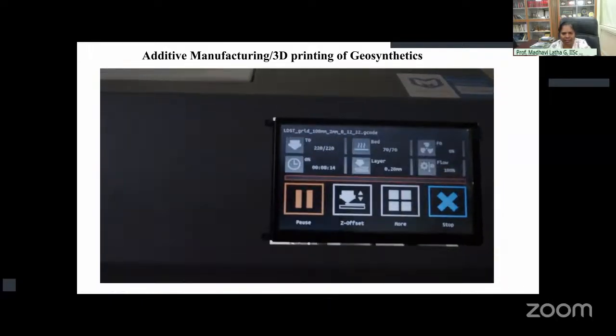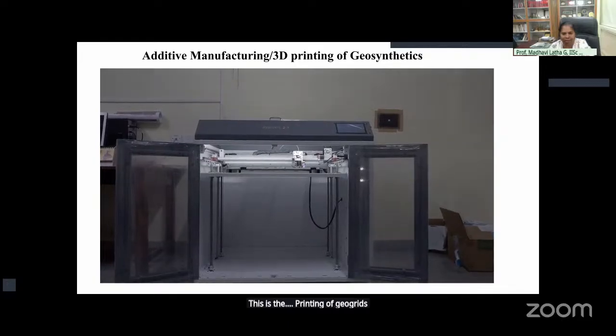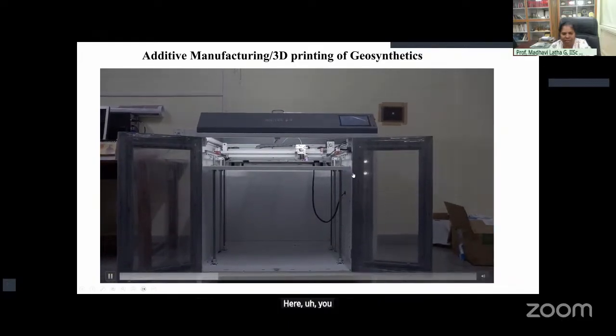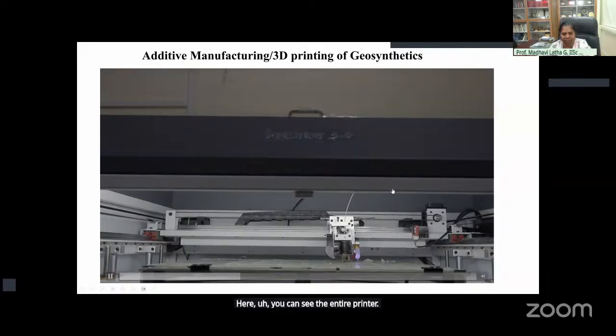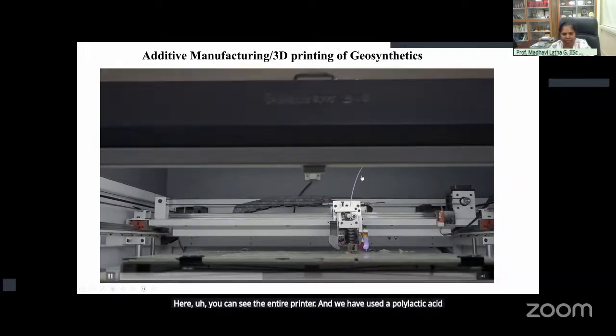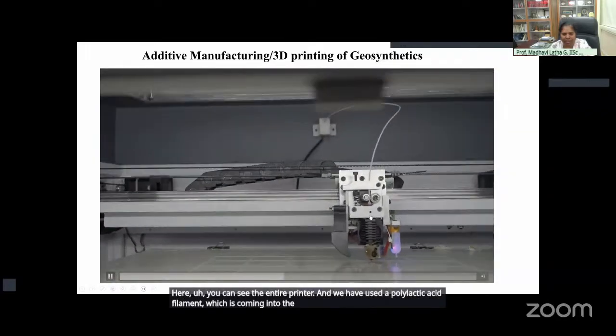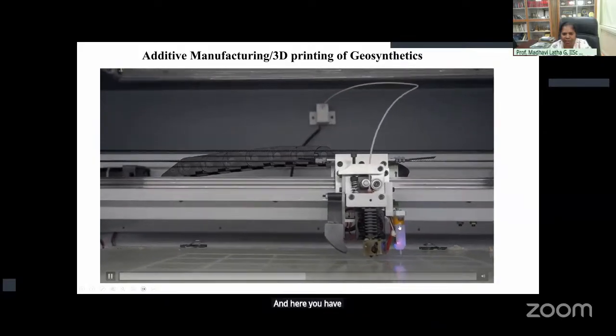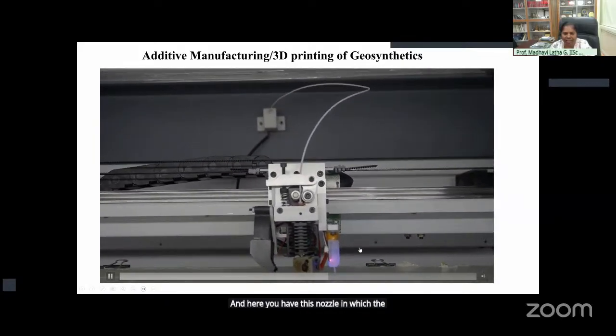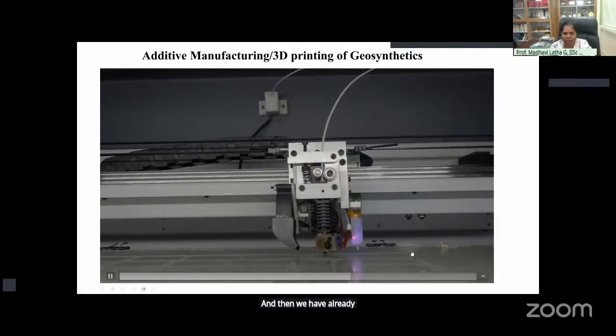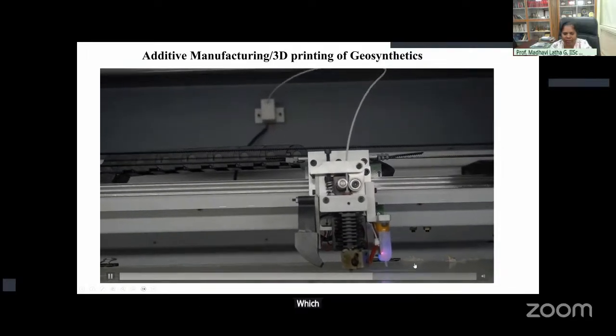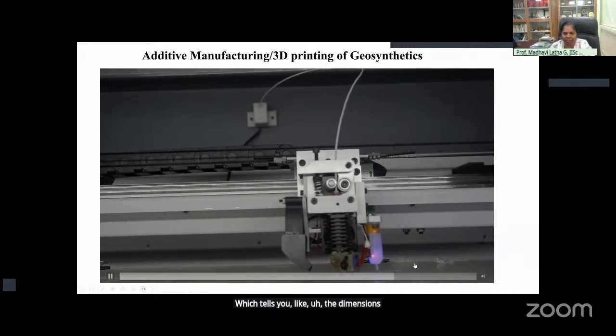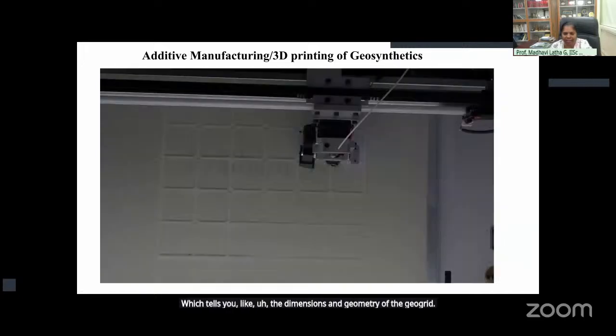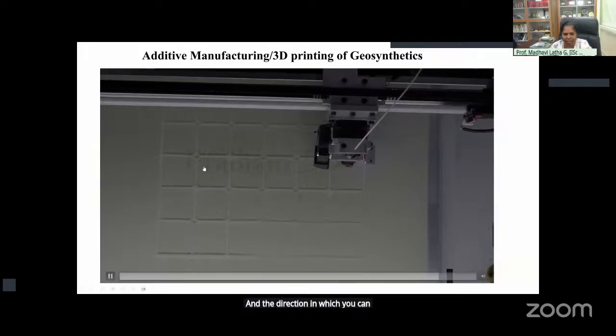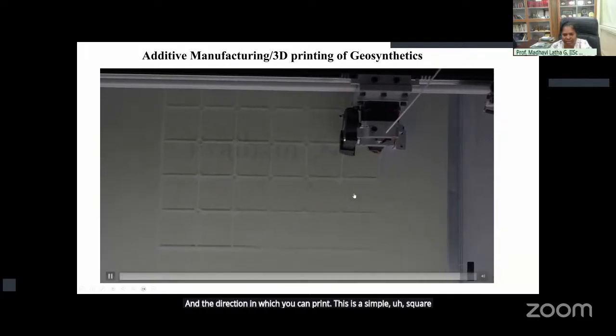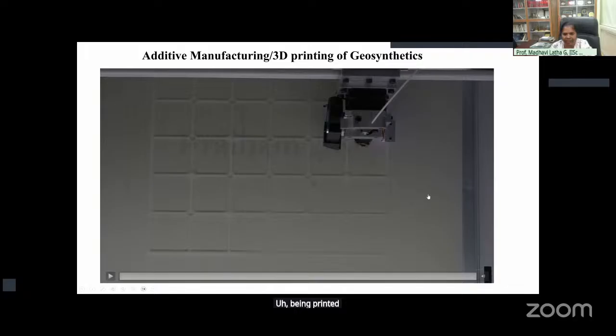This is the printing of geogrids that I'm mentioning about. Here you can see the entire printer, and we have used polylactic acid filament, which is coming into the extruder head. And here you have this nozzle in which the material melts. And then we have already given a G code to the system, which tells it the dimensions and geometry of the geogrid and the direction in which to print. This is a simple square geogrid which is being printed here.